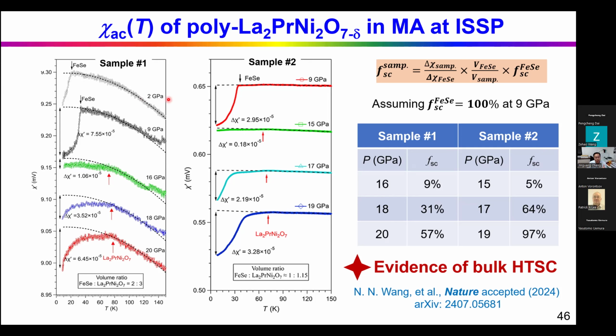And we measured two samples. The second sample shows much better data quality because we changed the excitation current and also the frequency. So the data quality becomes much better after the first measurement. We have more experience. So we can estimate the superconducting volume fraction by comparing the magnitude of this superconducting signal. Assume that iron selenium has 100% superconducting volume fraction at 9 GPa. Then we just make a simple calculation, so we can calculate the superconducting volume fraction for sample 1 and sample 2.